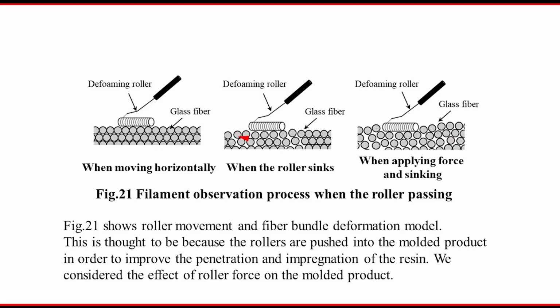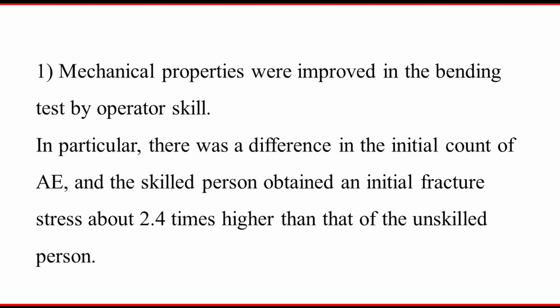And then we try to think about the fiber state, which is subject to that U movement. The defoaming roller, a steel roller, goes past on the surface of the glass fiber without any load, so there is no change. The glass fiber state is no change. But when we apply the load, there is a U-shaped deformation state. That means the glass fiber filament opens. And after that, the resin comes from the back. So therefore, this U-shaped movement of the fiber is related to the opening state of the fiber.